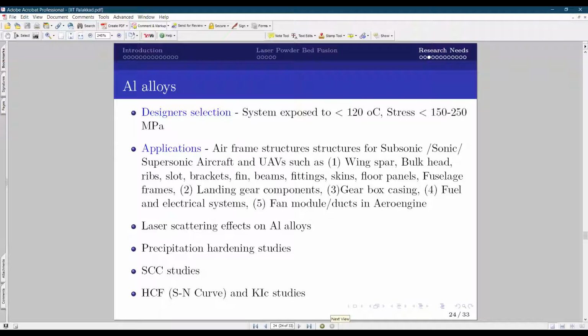And recently I came to know that 7050 alloys are 3D printable. But if you look at the 7 series alloys, all of them are prone to stress corrosion cracking. And based on the heat treatment you use, whether T73 is needed or not is still not known. So in these areas you can channelize your research and gather the data and let industry know that stress corrosion cracking is important for 3D printed aerospace.